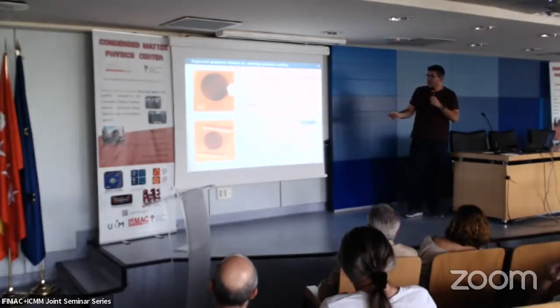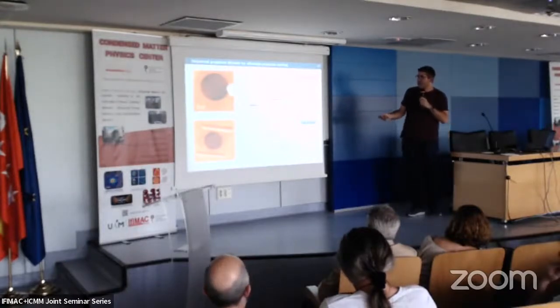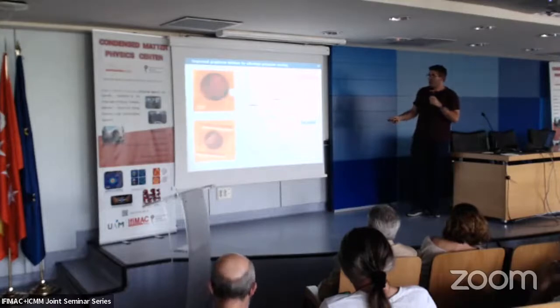Also, we studied mechanical properties on this. So we studied the indentations on graphene blisters, standard and sealed. And from force curve indentation, we can also get stress-strain maps. And we can see that in the pristine blisters, we can just reach, let's say, a given amount of strain. But when the blister is sealed, we can reach almost double the amount of strain. If we try to push harder, what we see is that wrinkles appear, and there is stick-slip behavior in these curves. And this is because, with these wrinkles, the shape is sliding.